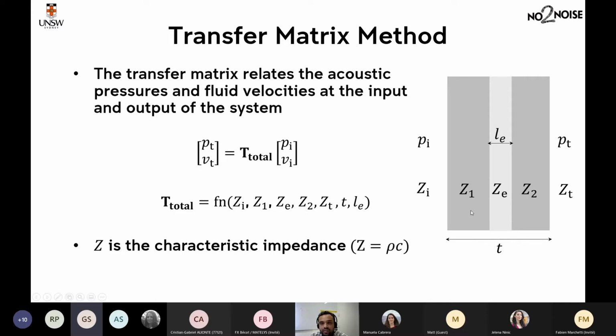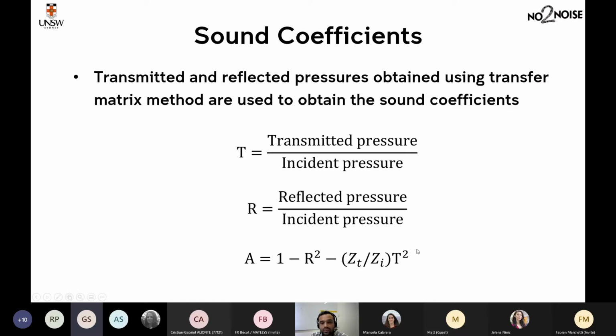So for our rubber medium, it is very easy to calculate the impedance. For our homogenized layer, we calculate effective density, effective bulk modulus, or effective longitudinal modulus. From there, we calculate effective sound speed, and then we just multiply the effective density with effective sound speed, and we get the effective impedance of the homogenized layer. So after this step, we use the total transfer matrix to calculate the reflected and transmitted pressures. And from there, we calculate the transmission, reflection, and absorption coefficients like this.